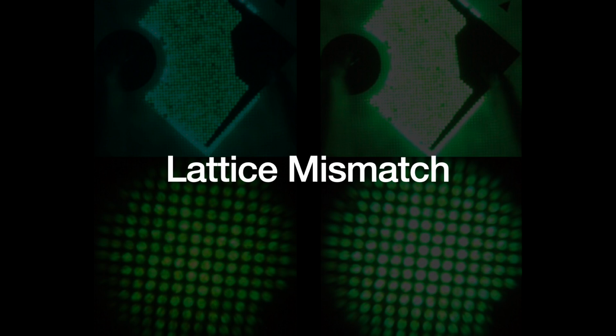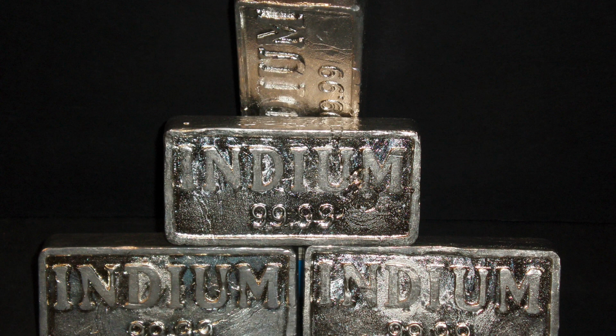Second, indium is unstable at higher temperatures, so micro-LED chips with higher levels of indium have to be grown at relatively lower temperatures, of about 600 degrees Celsius. Yet, these same lower temperatures can lead to crystal quality defects. Too many defects jack up the cost of fabrication. So, manufacturers have to compromise with middle temperatures, striking a balance between two bad situations.